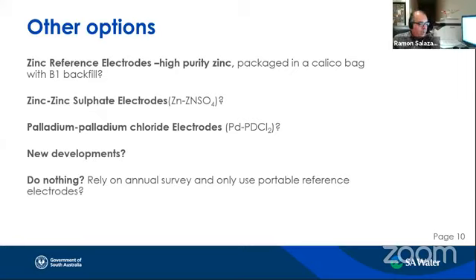I have to clarify that not all of the reference electrodes fail after 2 or 3 years. Some of them were installed in the past 4 or 5 years and are still working very well. We haven't conducted an investigation of why the reference electrodes are failing in 2 or 3 years. One thing I would like to do is, if they dry out, pick up some 3 or 4, pour water, and use the data logger to measure how quickly they regain functionality, if I can reactivate them, or check whether maybe it's not a problem with dry-out.